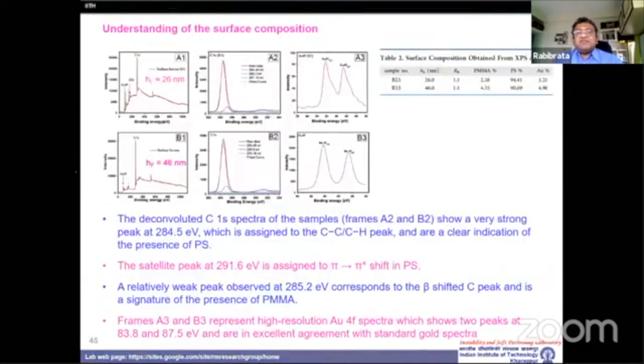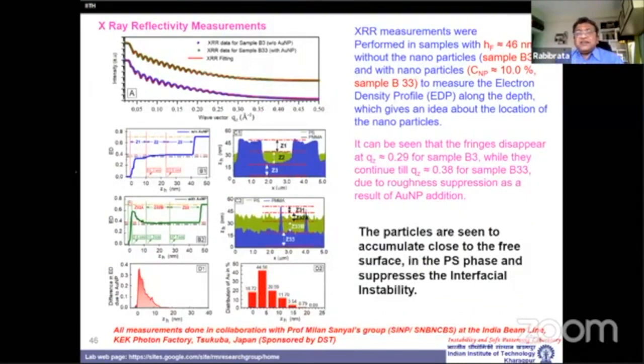We did some XPS and figured out that there is a signature of gold going to the free surface. So probably during the spin coating itself, along with evaporation and due to thermodynamic effects, some gold particles go to the free surface. But more interestingly, along with Professor Milan Sanyal's group at SINP and this flagship program of DST that's running on, we used the Indian beamline at Tsukuba and could find out the electron density profile along the depth of the samples.